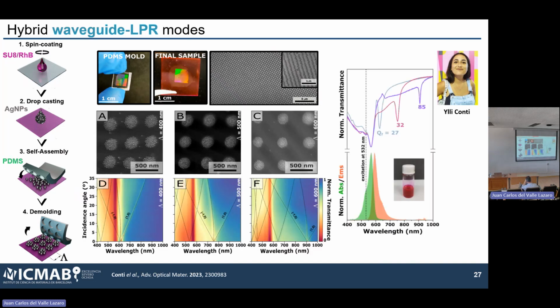And then we create our metasurface on top. As you can see here, this is how the sample looked. And these are just zoomed in pictures where you can see the cluster. These are 23 nanometer silver nanoparticles. So as you can see here, we did the same optical characterization that I explained before, changing the angle, so we could see these very sharp resonances that move.